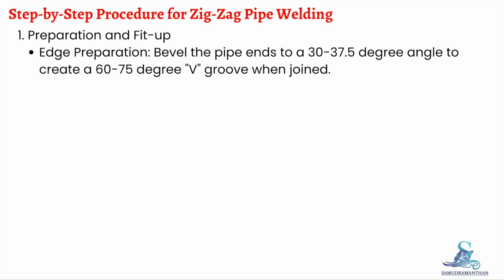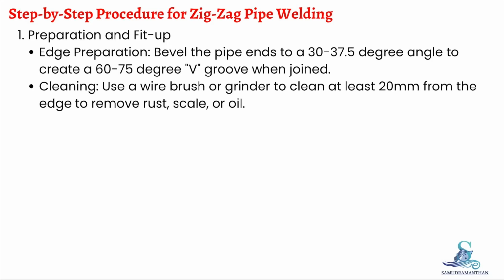Edge preparation: bevel the pipe ends to a 30 to 37.5 degree angle to create a 60 to 75 degree V-groove when joined. Cleaning: use a wire brush or grinder to clean at least 20 mm from the edge to remove rust, scale, or oil.